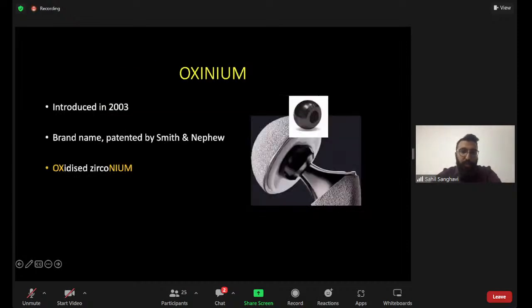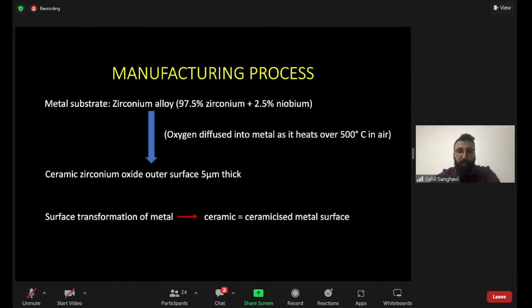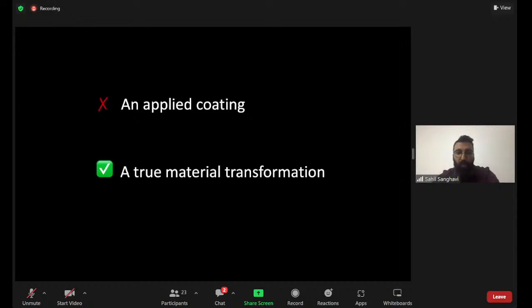Coming to Oxinium, this is basically patented by Smith & Nephew and it is oxidized zirconium. So it is a metal substrate of a zirconium alloy, wherein oxygen is diffused into the metal as it is heated over 500 degrees Celsius in air. So it is a ceramic zirconium oxide outer surface. It is actually a surface transformation of the metal to ceramic, or a ceramicized metal surface. So it is not an applied coating, as often it is a misconception, but it is a material transformation.